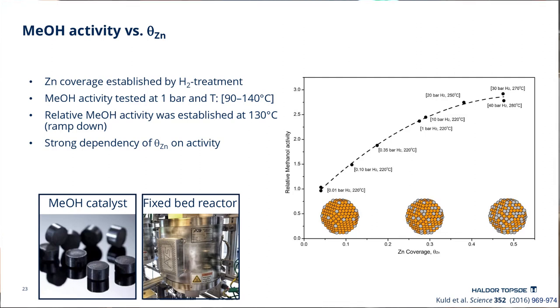And you can really see that when you go from the case where you have the pretreatment in a dilute concentration of hydrogen to where you really treat it in a lot of hydrogen, you see a huge difference in the methanol activity. So we benchmarked it at this plateau here at 130 degrees on the way down. And afterwards, we could actually directly measure the zinc coverage in the surface. So we can link this together, and you get a plot like this. Here you have the relative methanol activity as a function of the zinc coverage on your particles.